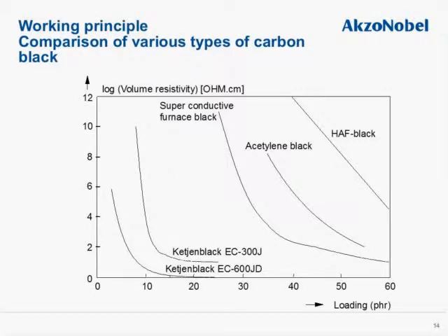Slight comparison. In this case, we measure resistivity, which is the opposite of conductivity. Obviously, as resistivity drops, conductivity increases based on loading. In this case, we're talking about phr, per hundred rubber. As I alluded to earlier, Ketjenblack EC-300J has a slightly lower conductivity, having a lower surface and lower pore volume than Ketjenblack EC-600JD. But once we start connecting those carbon particulates, the conductivity is increasing exponentially. And usually, for both these products, it is way below 10 phr.